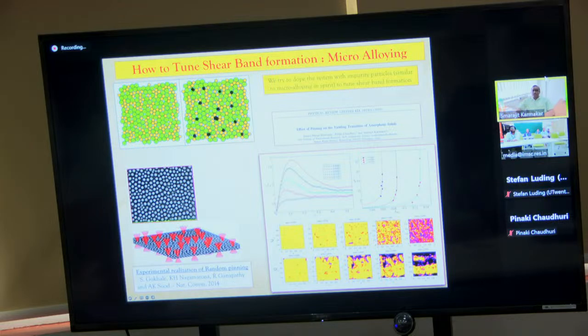So the concept that we used is this microalloying. Our crude model of microalloying was to actually fix a few particles, that we call pin particles, and we do it randomly, and this is the reason why this is called random pinning protocol. Using this method, you just choose a set of particles randomly and you freeze their position. But when you deform them, then they can move efficiently, but all non-affine motions are suppressed. And we looked at the yielding process in this kind of scenario.